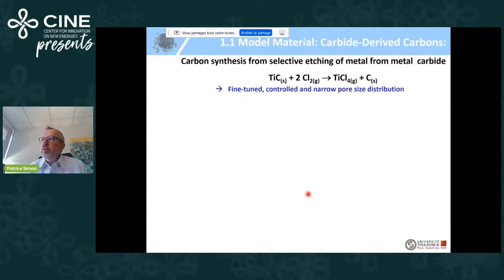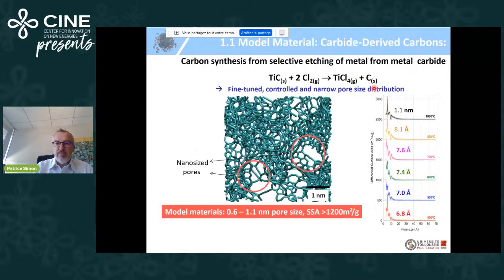And what we use as porous carbons are carbide derivative carbons, which are model materials for our studies. We are not only using these ones, and I will give you a couple of examples of what we do later. To prepare this CDC, carbide derivative carbon, porous carbons from metal carbide, we take a TiC powder, and we do a chlorination of this TiC powder at different temperatures, so that you remove the titanium part through gas phase, and you end up with carbons which are porous.